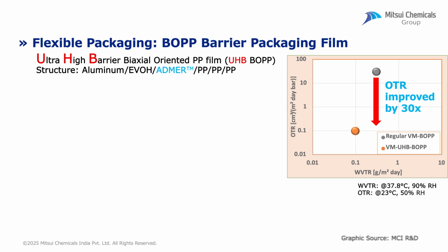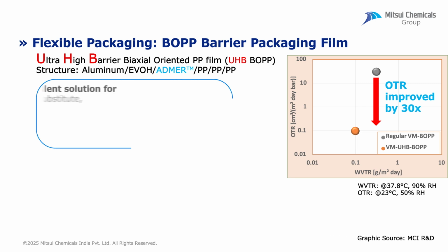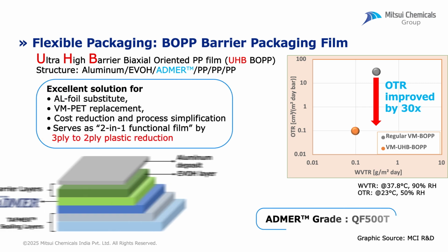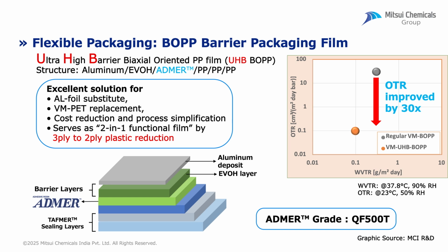Ultra high barrier BOPP film. Mitsui Chemical has an optimum solution to cater to high barrier requirements like 0.1, 0.1 OTR and WVTR values, which is an excellent solution for replacement of metallized PET and aluminum foil based film structures.